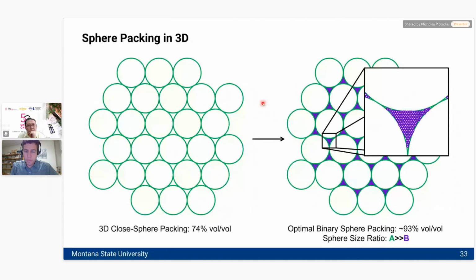Now, that number of 30% nano, 70% micron, I couldn't help but wonder if it had anything to do with the sphere packing ratio. As many of you might know, the highest close packing density that you can achieve is 74% volume per volume with spheres. Now, our particles are probably not exact spheres; they're probably not close packed. But I just thought that was too much of a coincidence not to at least think about.